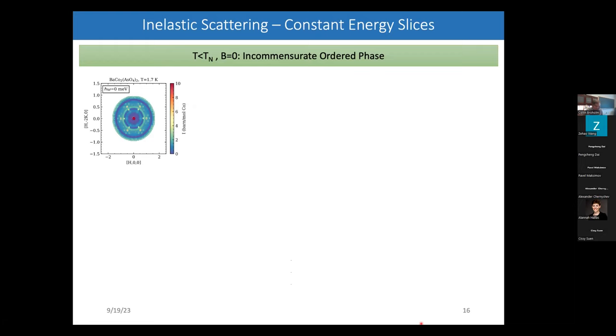So then let me see how I think about time. So then let me now begin to look at the inelastic scattering. And the point I want to make with this is that the material actually looks pretty much like a two-dimensional ferromagnet in its excitations. At least when I come up a little bit in field, when I help it, if you will, a little bit with an in-plane field, I can drive it into an easy plane ferromagnetic state. And then it really behaves like you'd expect for an easy plane ferromagnet. But when we remove the field and go into the incommensurate state, then we do see the effect that it's modulated and some additional complexities. But you really notice this kind of proximity to a 2D ferromagnet.